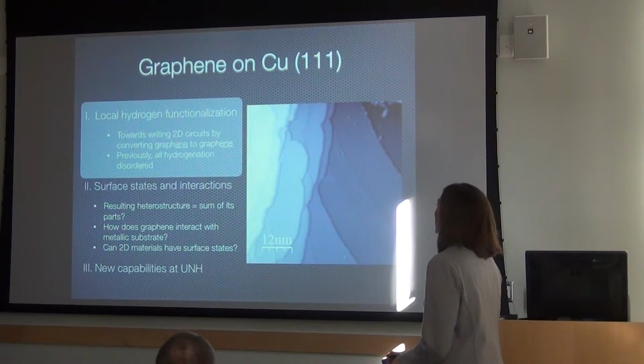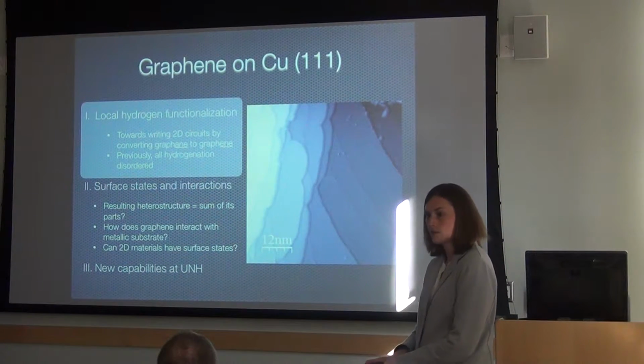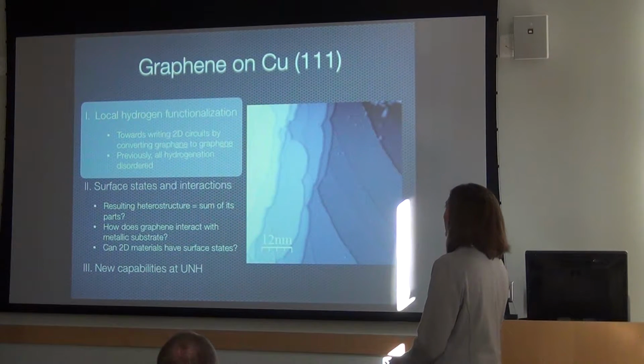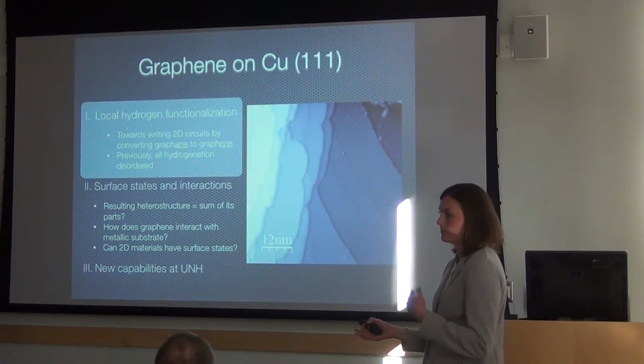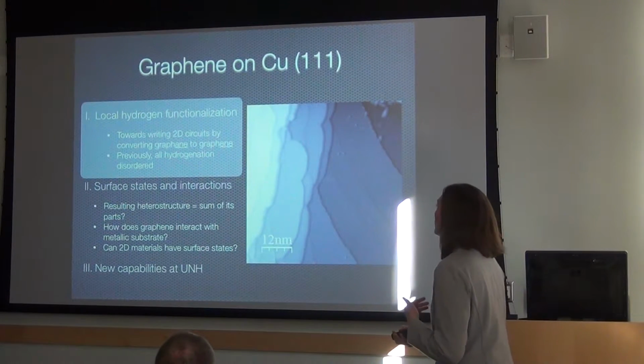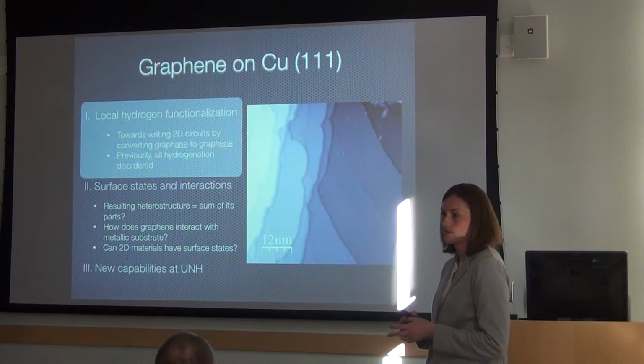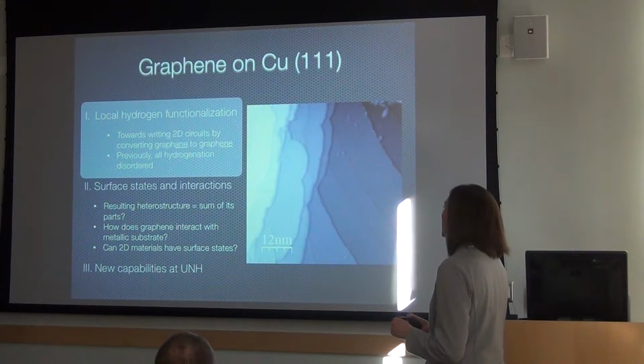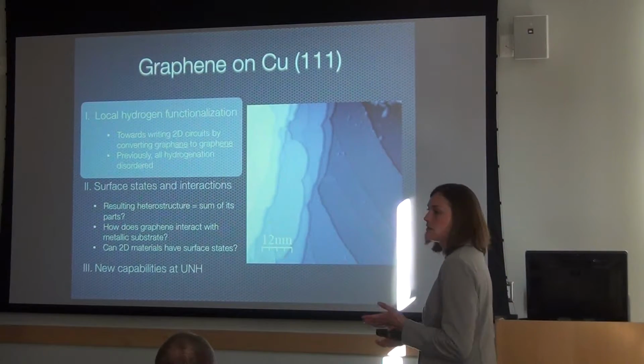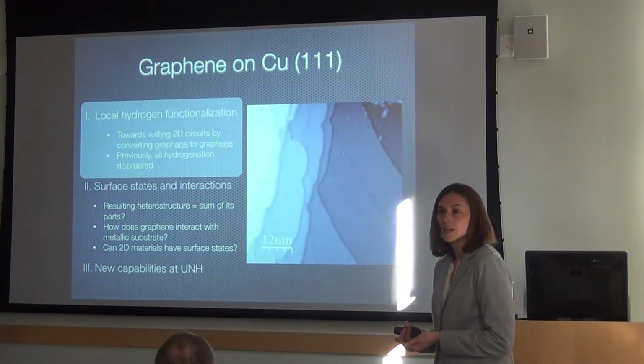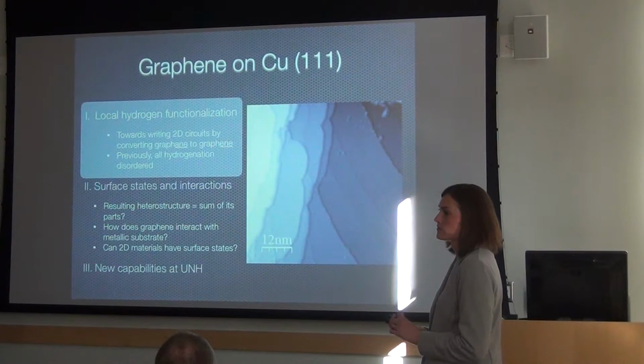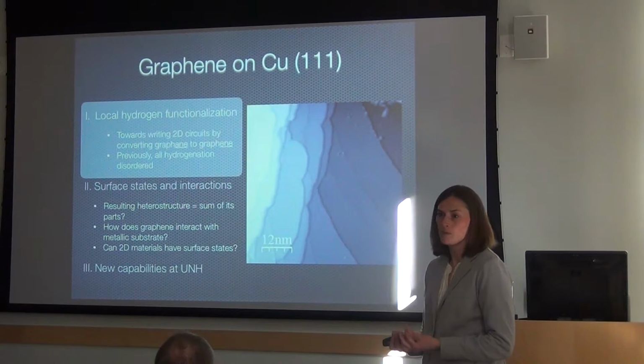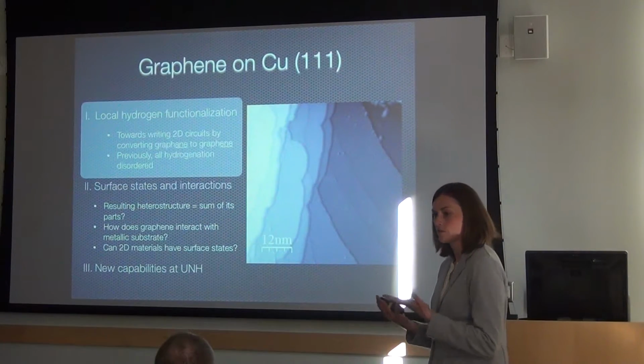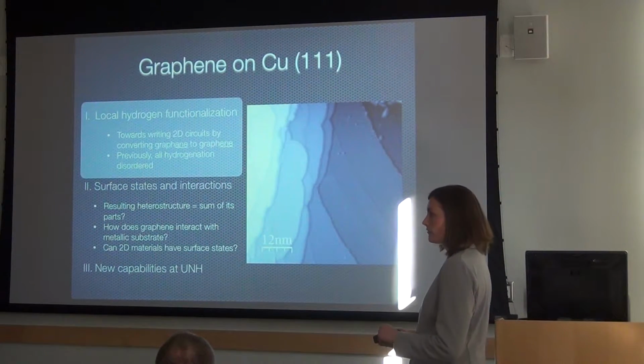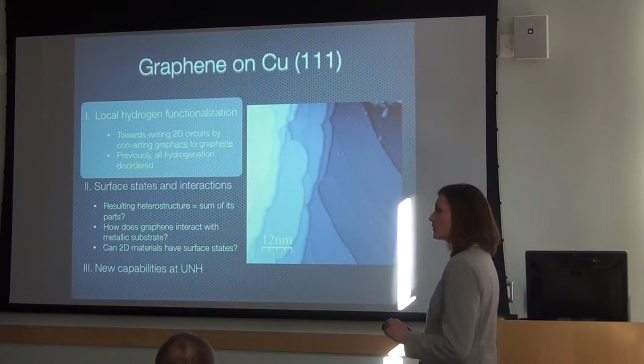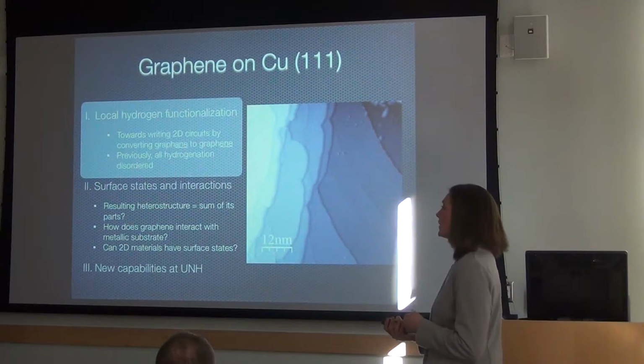So that's what I wanted to tell you about this local hydrogen functionalization that we were working on. The idea is to use hydrogen to locally functionalize graphene towards writing 2D circuits in a two-dimensional material. There has been other work in trying to hydrogenate graphene, and even some other STM work, but previous results are all disordered. So the fact that we were able to get something that looked like an ordered structure of hydrogen on graphene is the real difference between what we've done and what other people were doing.